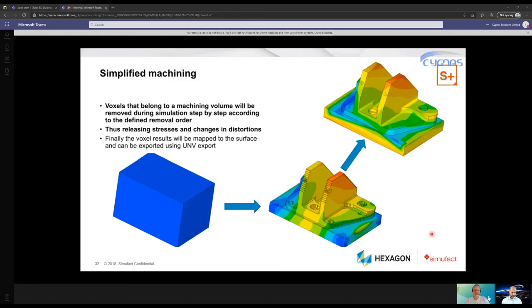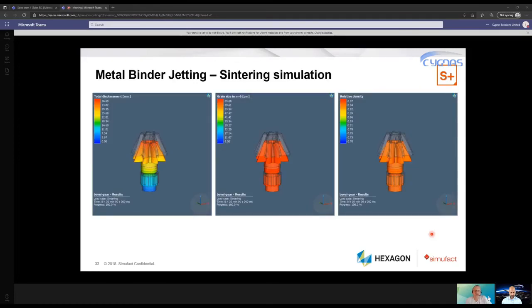It's fine. Okay. So in the latest release, we have also introduced a machining simulation, which is funny because we have additive manufacturing and of course included subtractive manufacturing, but it's a typical post-processing step that can also be simulated. And in metal binder jetting, we have the sintering simulation. In metal binder jetting, you do not have a laser that is melting particles, but you have a binder agent that is binding the powder particles. That means you have a sintering step afterwards.